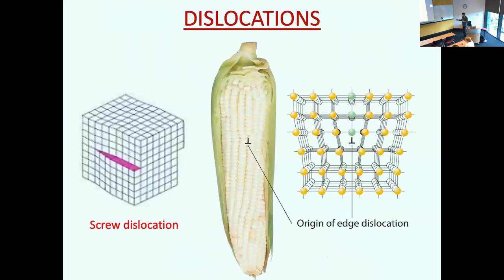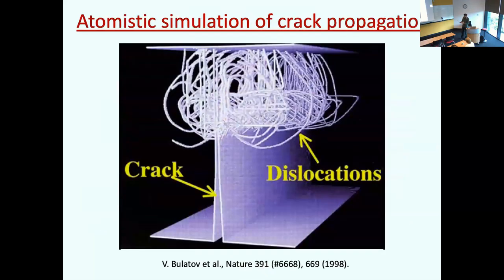So let's look at some pictures, then I'll come back to some interesting stuff. So dislocations. Missing planes, missing lines, like here in this maize, or you can have dislocations. So these are topological defects in materials. It's very important for the strength of material. Suppose you have crack propagation. If you look at the end of a crack, do some kind of interesting MD. At the crack tip, you have proliferation of these entangled dislocations, and that tells you how strong or brittle, etc., the material is. So this is a very important problem in material science.